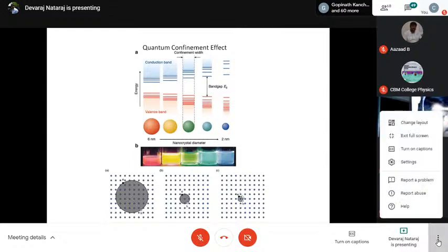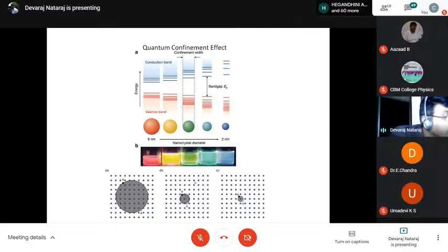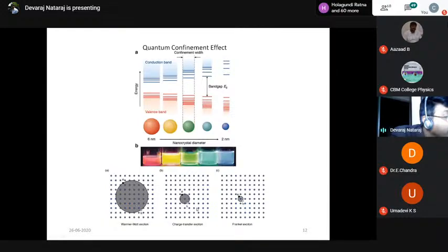You have one more exciton, the charge transfer exciton. Here also you have an electron-hole pair, and this is also made up of molecular crystals, but heterotype molecular crystals. You have two different types of molecules forming this material medium. So when you excite the system with photons, the electron will be introduced in one molecule and the hole in another molecule. Because of that, you call them charge transfer type excitons.